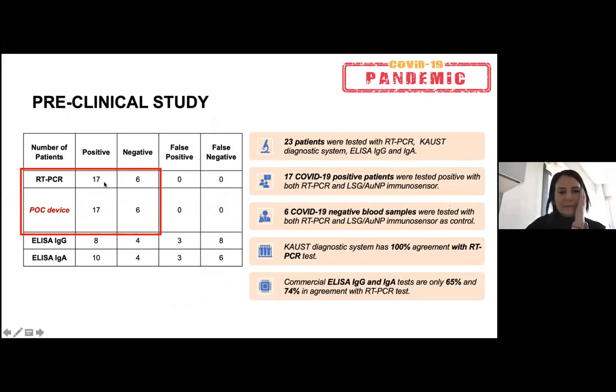So in the case of preclinical studies of the POC devices developed in this part, we compare our data with RT-PCR, that is the gold standard, and also with other tests, ELISA tests. What we can find is that our POC system has 100% agreement with the gold standard, and when we use commercial ELISA IgG and IgA tests, these are only 65% and 74% in agreement with this standard. So it means that it works well, and we are still working to make some improvements together with that group, Professor Salama.